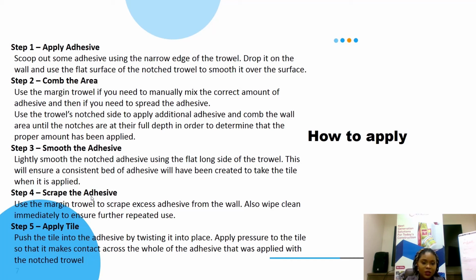So you scoop out some adhesive with your trowel, apply on the surface. Please note that it's not ideal to apply the tile adhesive on the tile, because it's almost impossible for you to spread the tile adhesive across the entire surface of the tile. So what happens when you don't spread it across the entire surface? You give room for empty drums under your tile, which is not a good thing to do. So it's best to apply your tile adhesive on the surface, spread it evenly with your notch trowel. The teeth of your notch trowel are going to determine the bed thickness of your tile adhesive, which will determine the coverage area of your tile adhesive.